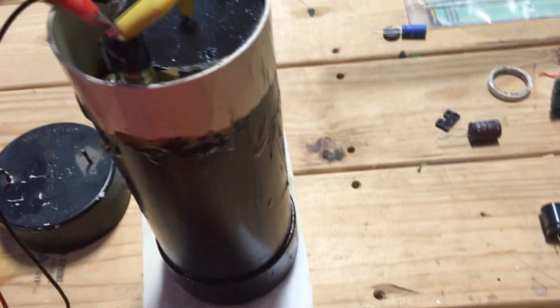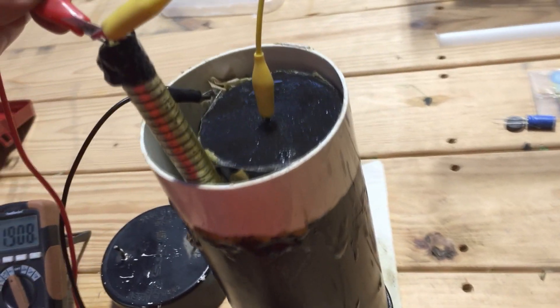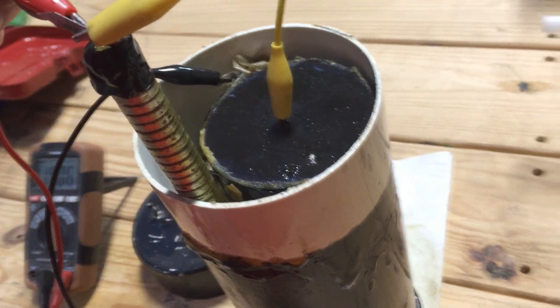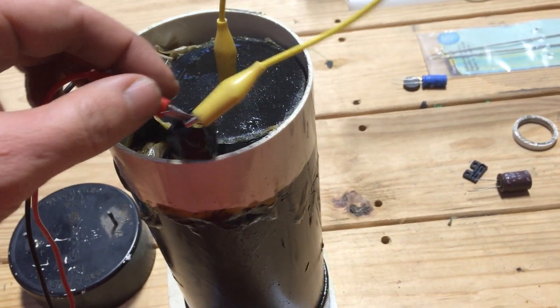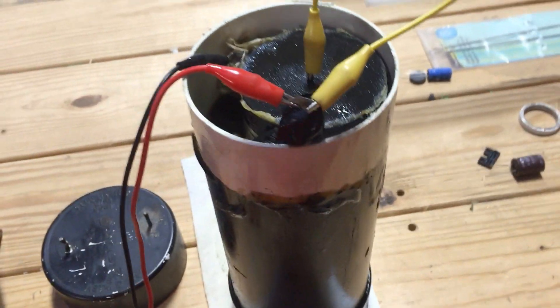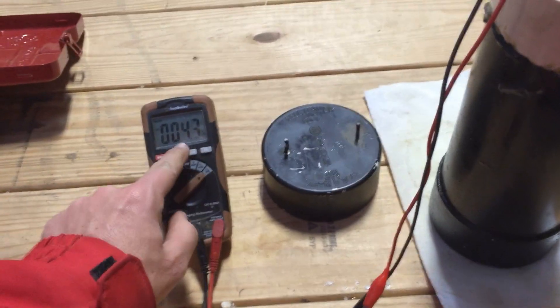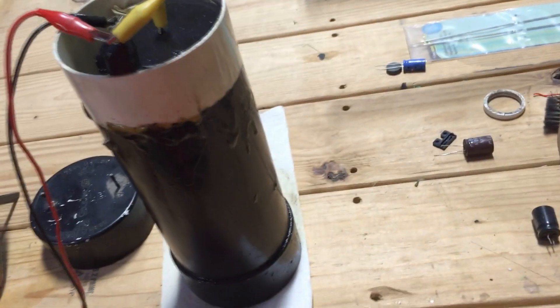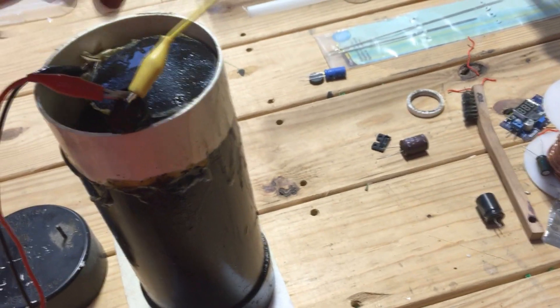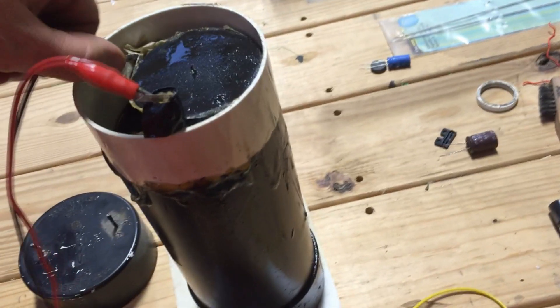There's a little one and you can see it right here, and the magnesium ribbon actually looks to be in really good shape for three years. As I take that apart we can inspect it more — there's a little one and a larger one. If I test the current on these, it'll default to the smallest one which is four micro amps, which is the reason it was running the little low current draw jewel ringer LED just fine because that took about a micro amp.